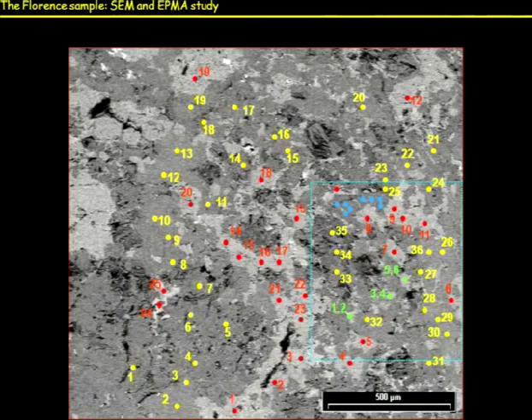Well, so what about the Florence samples? Just very quickly. So we tried to slice, okay? Let's slice the Florence samples, the 3 millimeter size samples, to see the internal structure. It was studied by scanning electron microscopy and electron microprobe. And you can see two levels of gray, so they are khatyrkite and cupalite intergrown together. And you can see all these points, yellow and red points, corresponding to khatyrkite and cupalite respectively, but it is not important. What I want is that you focus your attention on these two grains. We are talking of 60 micron grains with the yellow points inside.